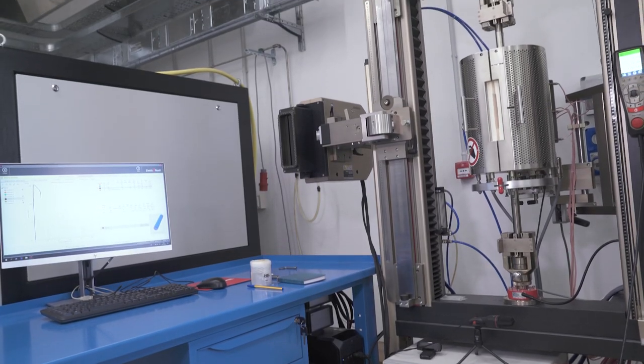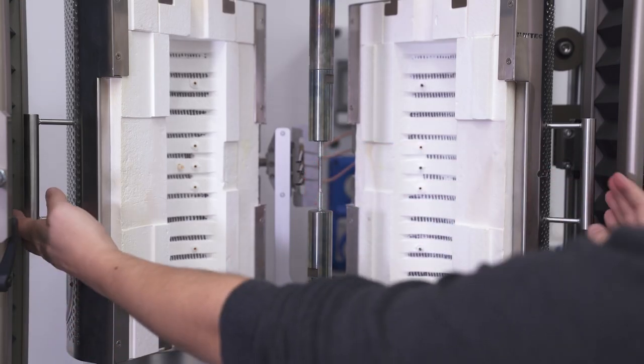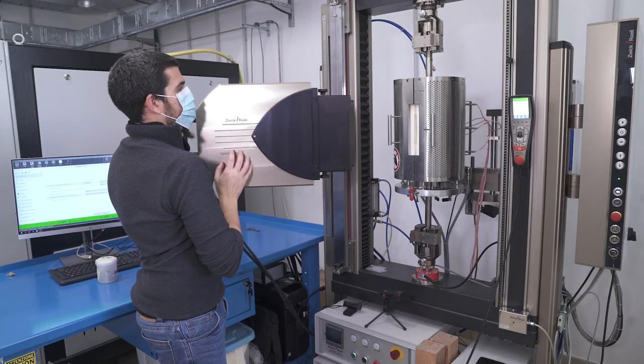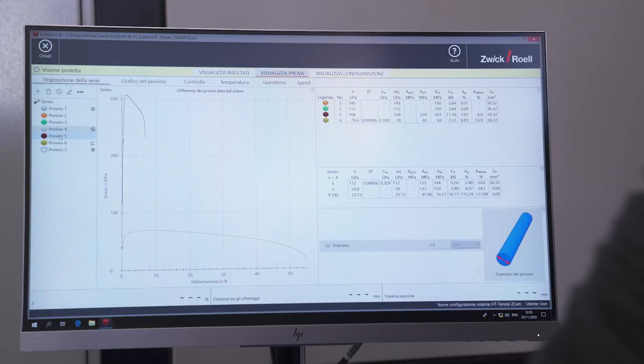Universal tensile compression machine operating up to 1200 degrees Celsius with a loading cell of 50 kN equipped with high-precision laser extensometer in micro and macro range with 0.7 microns of resolution.